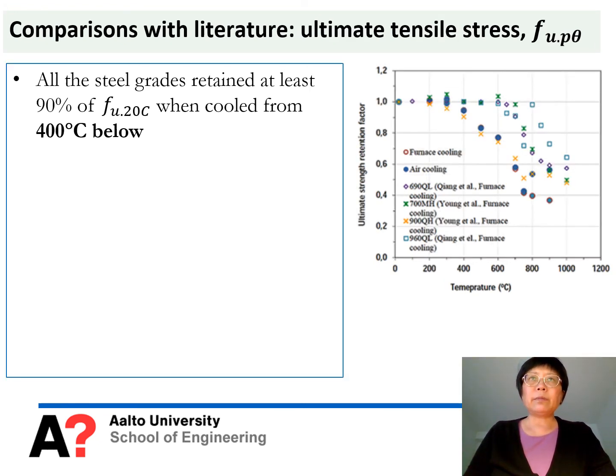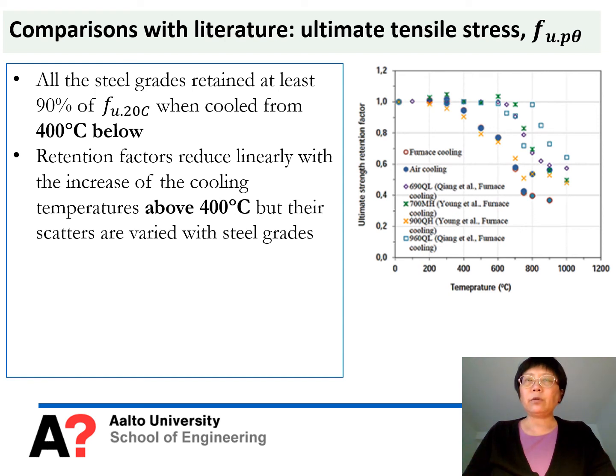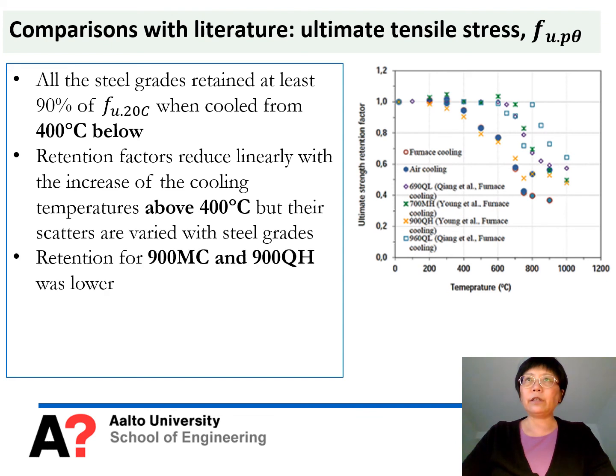And this slide basically shows the comparison result on ultimate tensile stress between different studies. It can be seen that starting from a cooling temperature of 400, all the steel grades retained at least 90% of the strength. And after that, the retention factor reduced linearly with the increase of cooling temperature, and the difference varied from steel to steel.